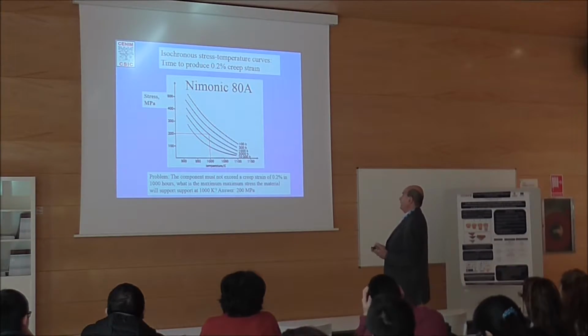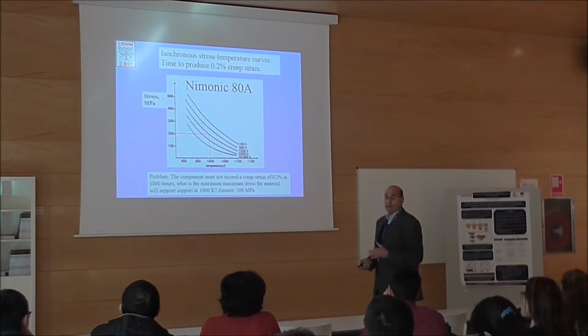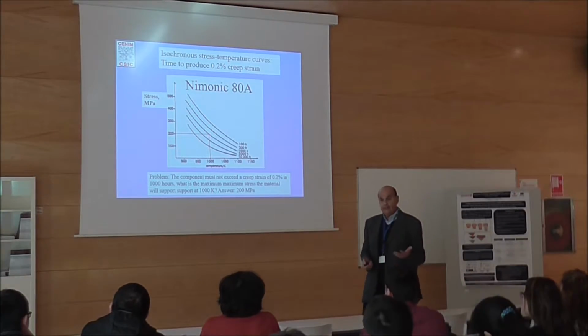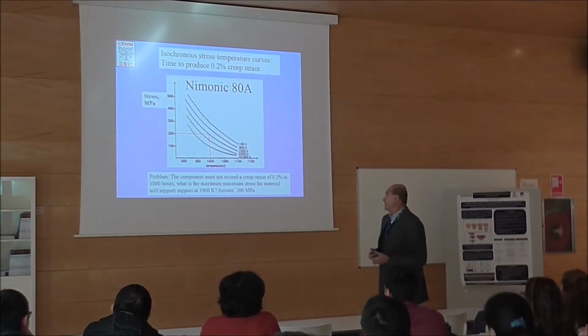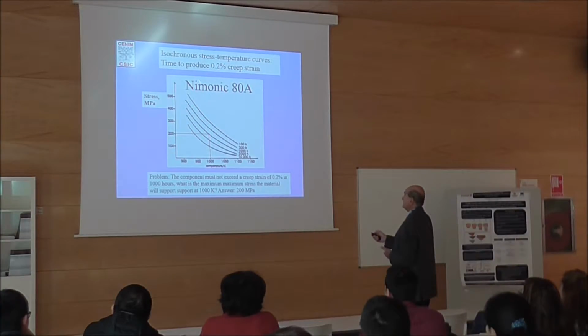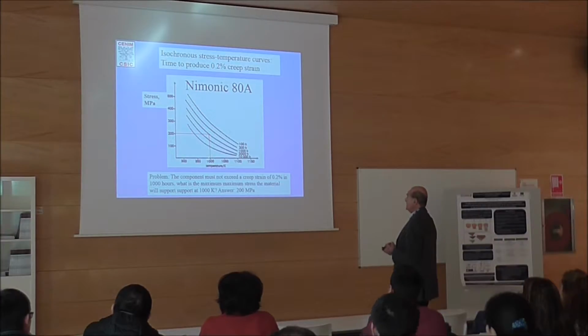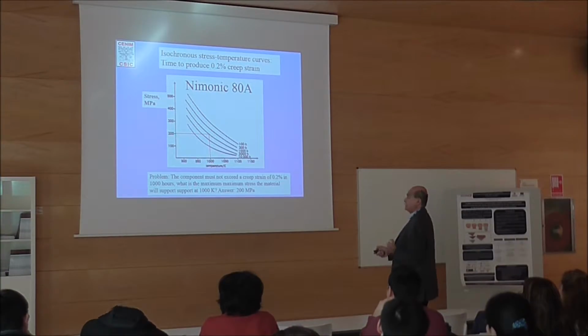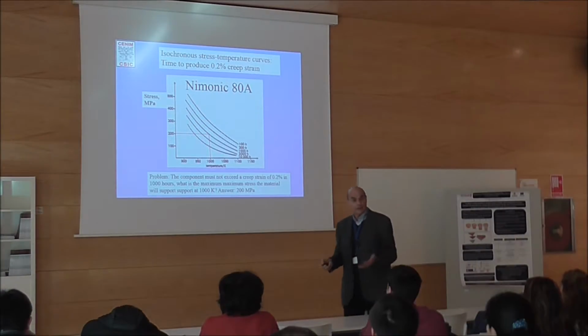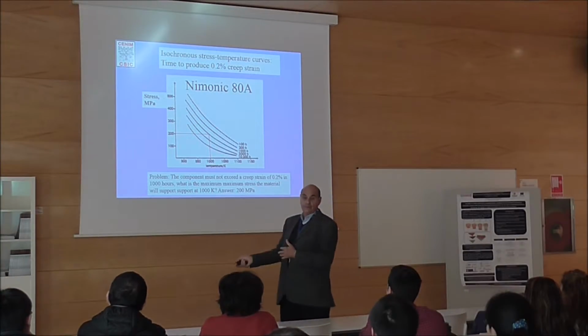and then we have the problem of, usually a component you allow to have 0.2% deformation. Doesn't matter if you have less than that. And then this curve, isochronous stress-temperature curves, predict, for instance, what is the maximum stress that the material can support, for instance, at 1,000 Kelvin. So you go here, and then the maximum stress is 200. This is predictions without being 5 years tested.